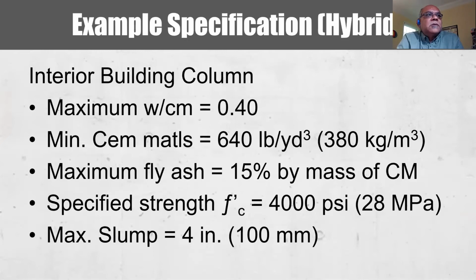And again, for an interior building column where you don't have an exposure to the environment, and therefore there's no specific durability concern, you have contradictory requirements that can get you considerably different mixtures in a bid process. You have a maximum water cement ratio, really not necessary because the only performance requirement for this interior building column, let's say it's not too much for high rise, is the strength requirement. But you have limitations on the maximum water cement ratio. You have minimum cementitious material content. You have a maximum limit on the fly ash. And then something that can adversely impact constructability is a maximum slump limit, okay?